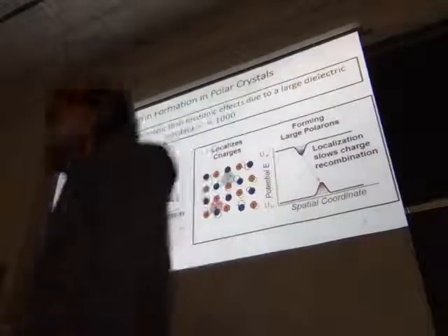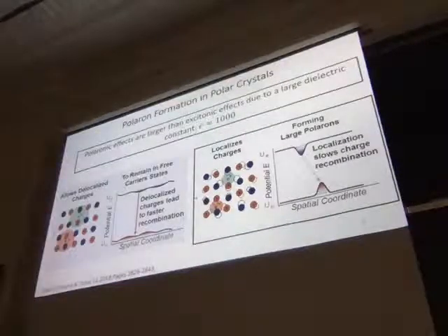So let's consider if you put photoexcited carriers in a box. Typically nanocrystals are more covalently bonded, but they don't have ionic charges in them. But these perovskites are a little bit more unique because they're polar crystals. And so instead of excitonic contributions being more dominant, it's going to be polarons. Polarons are going to be more prevalent to form in the excited state than excitons. And that's mostly due to the very high dielectric screening in these materials.